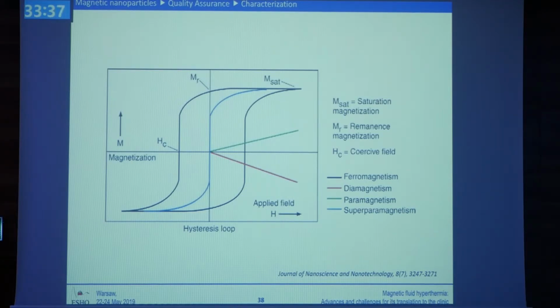So in the beginning it changes like that, and it is true that when you reverse the magnetic field, the magnetization follows a different path. And for ferromagnetism, this makes what we call the hysteresis loop. So in ferromagnetism, because of the anisotropy energy, the magnetocrystalline energy, which I will not come into in many details, when we apply the external field and we reverse it, we have a different behavior of the total vector of all the different magnets inside your material.